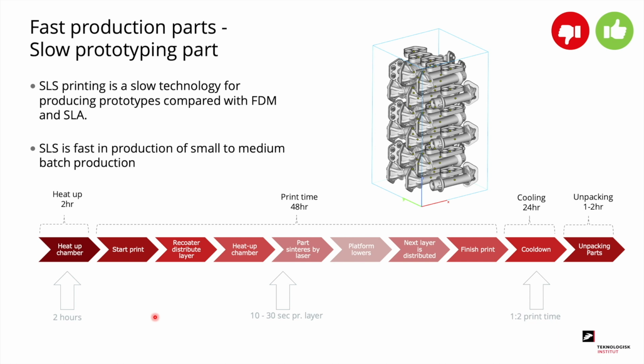Typically it takes about 2 hours to warm up the chamber to about 180 degrees. The entire print process with all of the layers to be built typically takes about 48 hours, where each layer takes about 10 to 30 seconds. Once it's been running, it has to cool down, and the cooling time is typically about half the time it took to print. So in this case, it must be cooled down for about 24 hours before you can start to break out the parts. Breaking out the parts, depending on how many and how complex, takes about 1 to 2 hours, but it completely depends on the number of parts and the geometry.